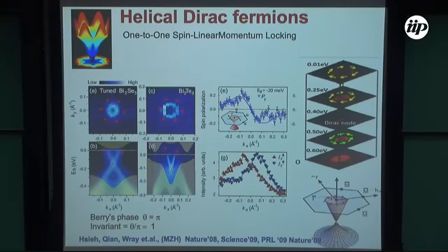And if we do a spin scan, then we see it's polarization down and polarization up with respect to some reference. But what matters is that polarization is reversing as you go around the Fermi surface. This is kind of like half Rashba. In a Rashba case, you have two copies of the Fermi surface, right? So when you have one single copy, you immediately see that the Berry phase is half of Rashba. In this case, it's pi Berry phase. So there is something non-trivial about it.